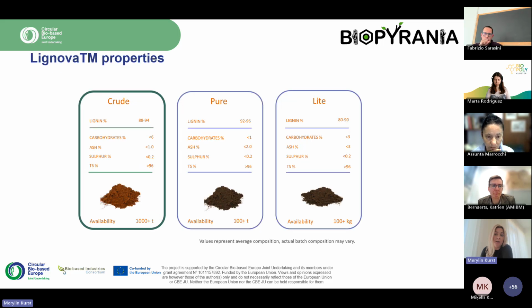For lignin, we have crude, pure, and light grades, each obtained at different stages of our process. For example, crude lignin is derived from the C6 process and has a slightly lower lignin content. In contrast, pure lignin is obtained from the MCC production process, where the lignin content is higher and the carbohydrate content is lower.